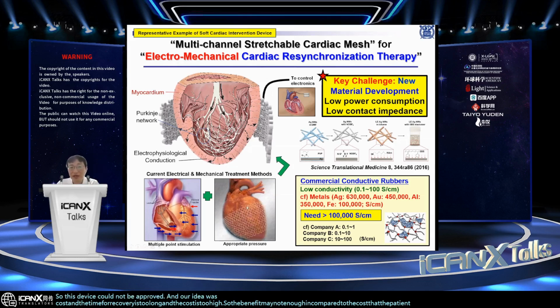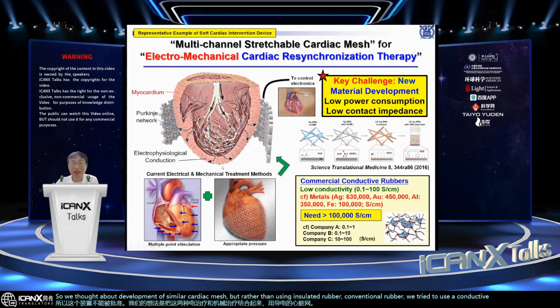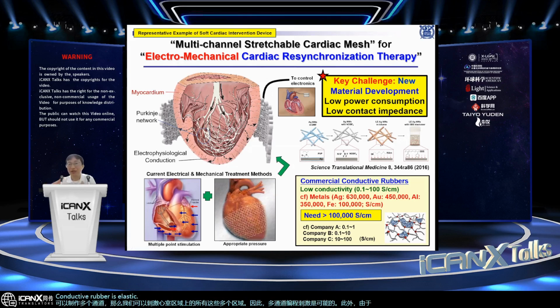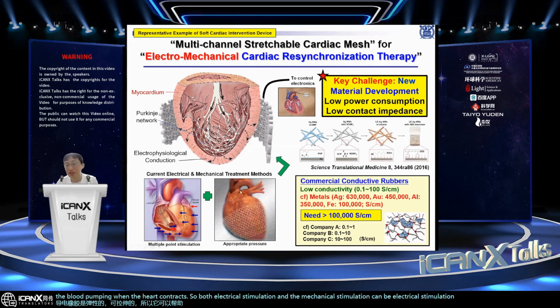And our idea was to combine these two, electrical therapy as well as mechanical therapy, by using a conductive cardiac mesh. So we thought about developing a similar cardiac mesh, but rather than using insulative, conventional rubber, we tried to use a conductive rubber. And if we can make multiple channels, then we can stimulate all these multiple areas on the ventricle region. So multi-channel programmed stimulation can be possible. Also, since the conductive rubber is elastic and stretchable, it can assist the blood pumping when the heart contracts. So electrical stimulation therapy as well as mechanical therapy can be achieved. Also, multi-channel cardiac modulation can be achieved.